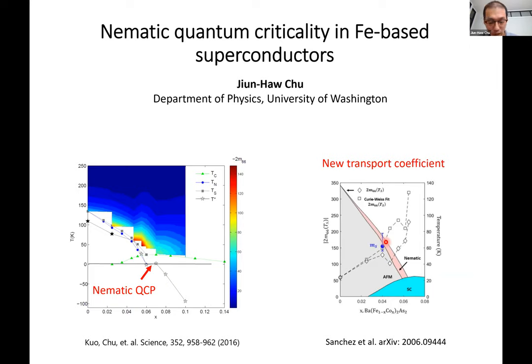We believe that this quantity is a way to measure the electron-lattice coupling of the materials in the nematic state. What we find is that this quantity increases significantly as we approach a nematic quantum critical point, by almost fourfold. This tells us that even as you suppress the nematicity in these materials, the electrons are becoming more and more sensitive to the lattice, possibly having to do with the high temperature superconductivity in this material.